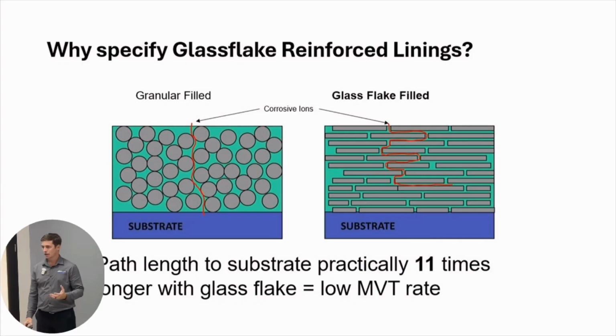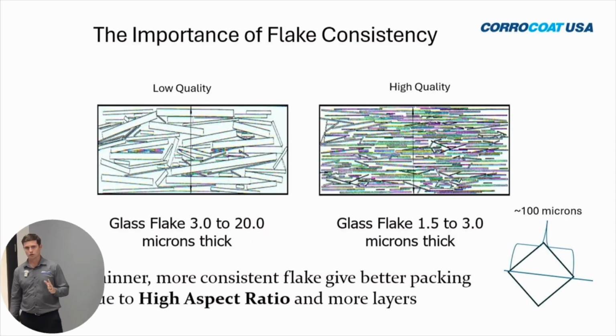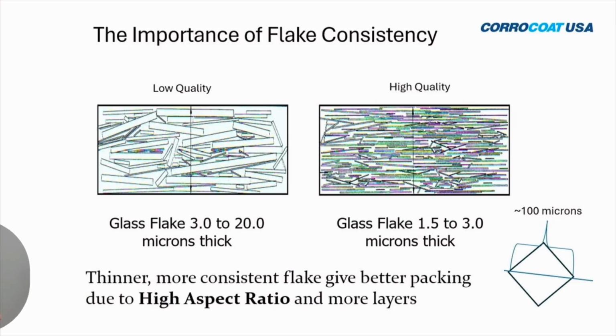Within that layer, you've created a situation where you lose momentum, and now you have a liquid-applied barrier coating. Without the glass flakes, or something that has a shape and will line up like that, you have to put more coating on to get the same resistance to permeation. There are some coatings and resins that are highly functional, but it never works out as well as when you use glass flake. As we'll talk about earlier, sometimes we do have certain situations where glass is not the best flake to put in, and we have substitute flakes. So obviously it doesn't line up just like the cartoon, if only.